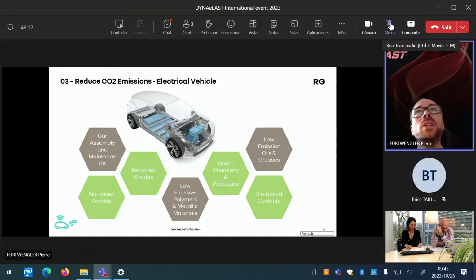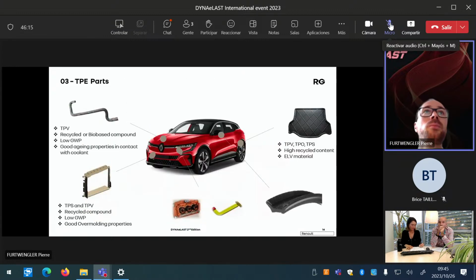To give you a quick overview of what we have as TPE parts in our car, we have several hoses. They are mainly in TPV. They can be recycled or bio-based compound with a low global warming potential. Low global warming potential because in most cases they will replace EPDM, and because of the curing step and the process, which is closer to a batch process, we have higher emission with EPDM. So each time we can replace EPDM by TPV, you decrease the CO2 emission of the cars.